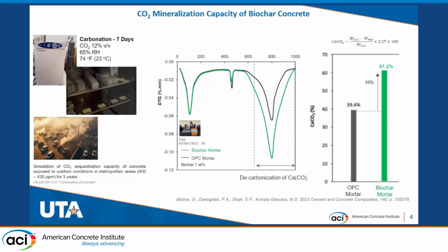We evaluated the carbon sequestration potential, the carbon capture and mineralization capacity, of this biochar concrete with a dosage of 1% per weight of cement. And we followed a specific carbonation regime. After 3 days of conventional curing, the specimens were moved to a carbonation chamber with 12% CO2 concentration and 65% relative humidity for 7 days, which corresponds to 10 days: 3 days of moist curing and 7 days of carbonation curing.